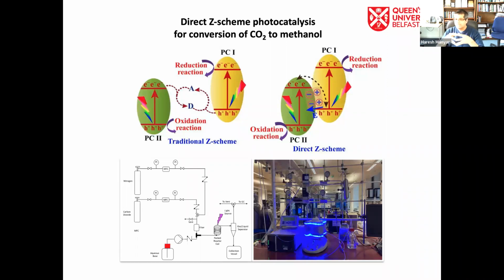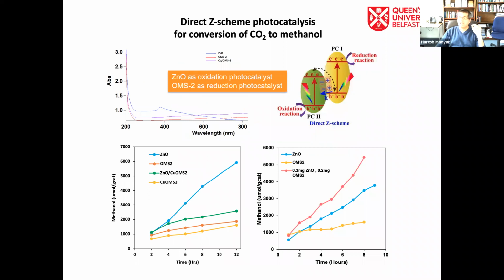In our reactor, we can shine two different types of light at the same time. We can not only control the wavelength of the light, we can also control the intensity of the light, and we can change from batch to continuous flow type of reactor. As you can see on the next slide, we have two different metal oxides. We have zinc oxide as the oxidation photocatalyst and manganese oxide as the reduction photocatalyst.